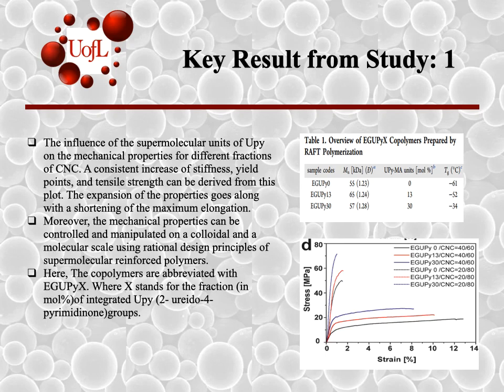The key results from the study. Here the table shows an overview of copolymers that are prepared by RAFT polymerization. Also, the plot shows the influence of the UPy on the mechanical properties for different fractions of CNC. A consistent increase of stiffness, yield points, and tensile strength can be derived from this plot. The expansion of the properties goes along with a shortening of the maximum elongation. In the less reinforced materials, the composition of polymer and CNC is about 40 to 60. They found the UPy content controls the elastic and inelastic properties.